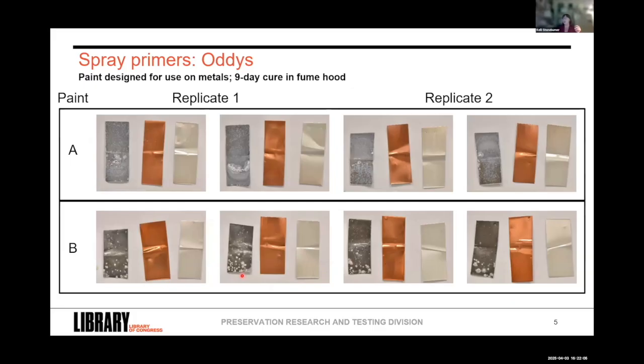The lead coupons covered in variety of different types of corrosion. Didn't image super well, but our silver in paint A has some slight hints of brown tarnishing, and the copper, some really faint discoloration on the part of the coupon that hangs closer proximity to the sample. So not ideal.